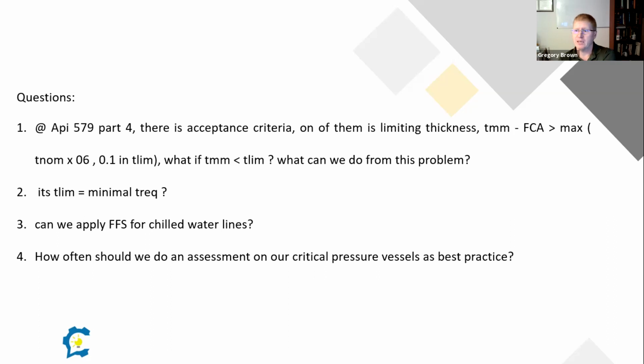And then for piping in the current version, that 1/10 of an inch requirement has actually been relaxed to 0.05 because there's thin wall piping. So really, if you don't meet that requirement, your only option is really to do a level 3 analysis to have some reason why you could operate that equipment when you're below that limiting thickness.